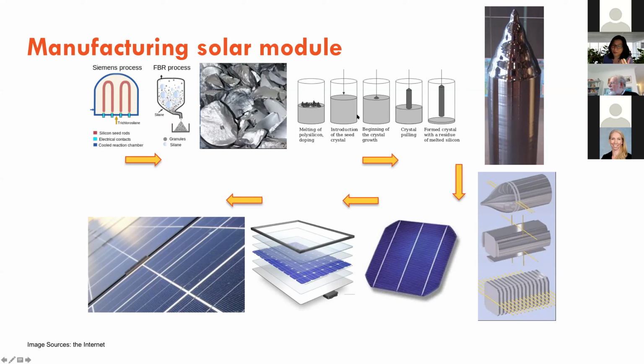You melt the silicon into this crucible, and the whole idea is to push all the impurities onto the ends of the crucible. You will have certain impurities on the top and certain impurities on the bottom, and you end up with this ingot. Then you slice this ingot into what we call wafers. It's a piece of silicon wafer, and then you can dope it using phosphorus or boron to make it P-type or N-type to form that PN junction. The PN junction is there to separate the charges.